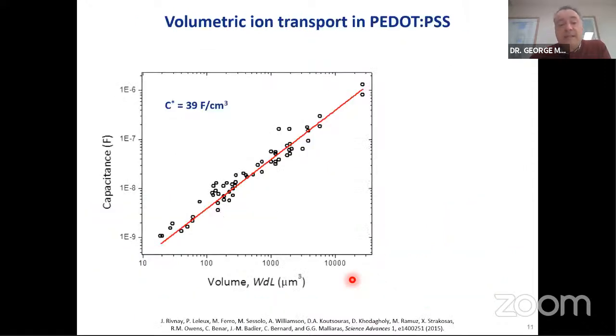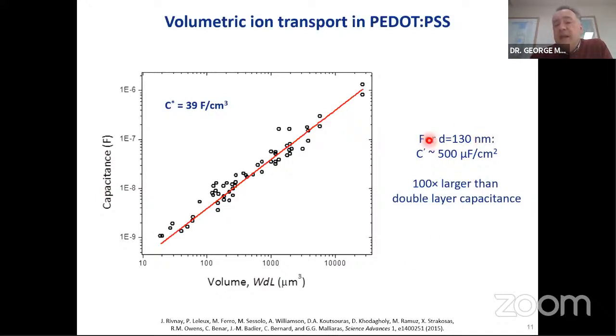The manifestation of this volumetric coupling is shown here. If you measure the capacitance of a PEDOT:PSS electrode, you will find that it scales not only with its area, but also with its thickness. So it scales with the volume, which means that ions can penetrate and distribute within the volume of the film. The ramification of this is that if you have a film of just a bit over 100 nanometers thick, you can get capacitances per unit area that are 2 orders of magnitude larger than what the double layer capacitance limit tells you. And as a result, you can now make electrodes that are much smaller that can record neural activity with higher precision. So in a sense, you gain in spatial resolution.